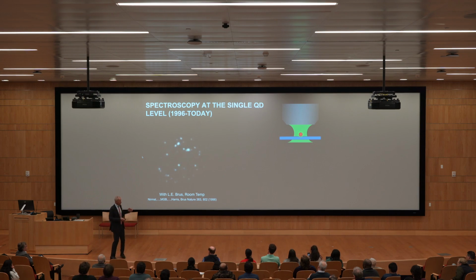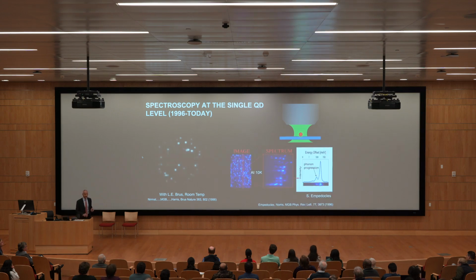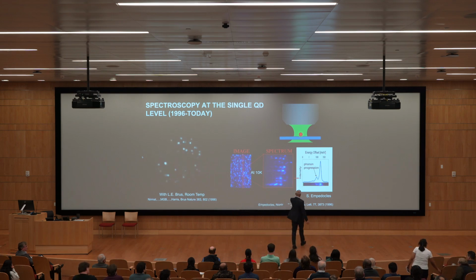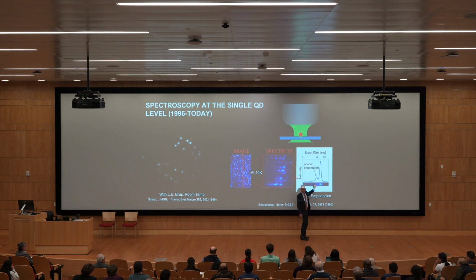If you go to low temperature, you start learning about the physics of them in a way you couldn't before, in a way that was hidden by the fact you still had an inhomogeneous distribution of stuff. Now you can look at one at a time, and you see things like vibrations, which we call phonons in the solid state. Now you can start to study how vibrations change as a function of size. So going to 4 Kelvin unlocks really interesting physics, and we're still doing that today.